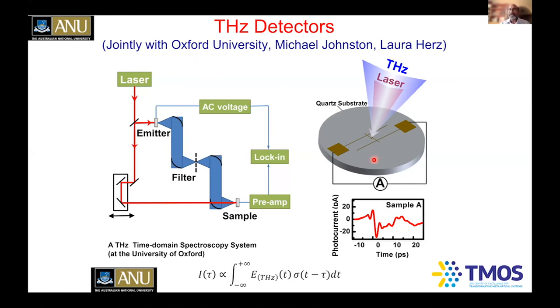What Kun Peng has done is take these nanowires, transfer them onto a quartz substrate, and make electrical contacts using electron beam lithography. Then comes a laser pulse that creates electron-hole pairs, photocarriers, and then comes the terahertz pulse, and the electric field of the terahertz pulse separates these carriers between the two contacts to measure the photocurrent as a function of time. If you can measure the photocurrent as a function of time, you can measure the electric field of the terahertz pulse and also the conductivity of the material.